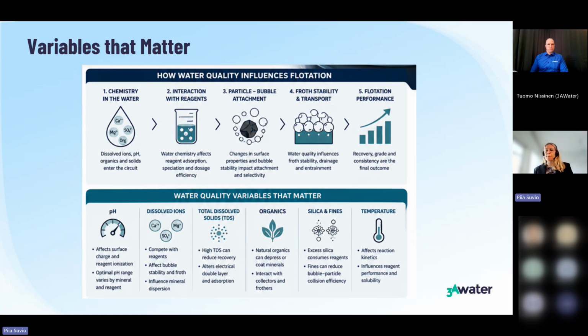Overall, silica and fine suspended solids in the water consume the reagents and can also reduce the bubble-particle collision efficiency. Then we have the temperature. This affects the reaction kinetics, and temperature is particularly important with sulfide ores because that can lead to a change in the pH, and that can then, of course, again alter the pH window. So temperature in some cases can be a very huge issue.